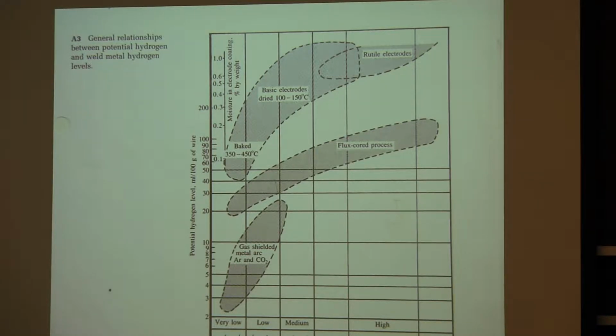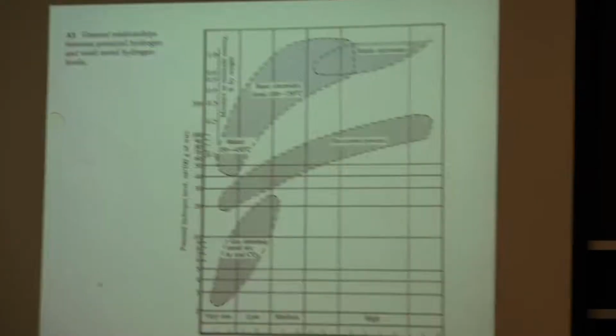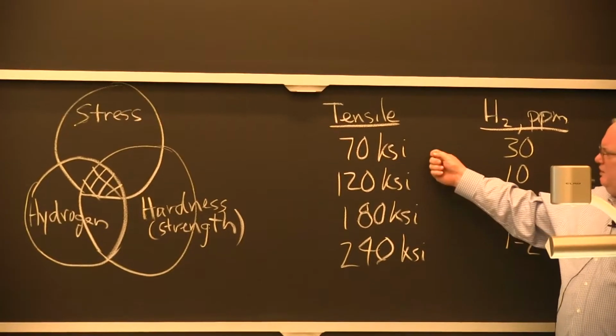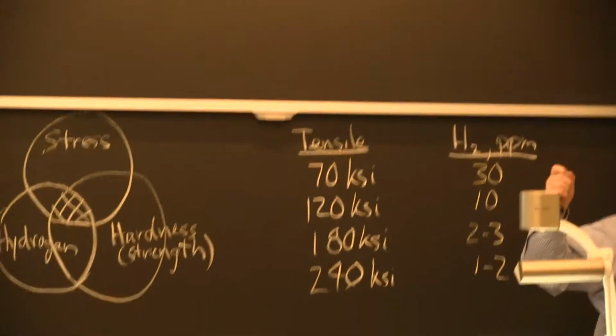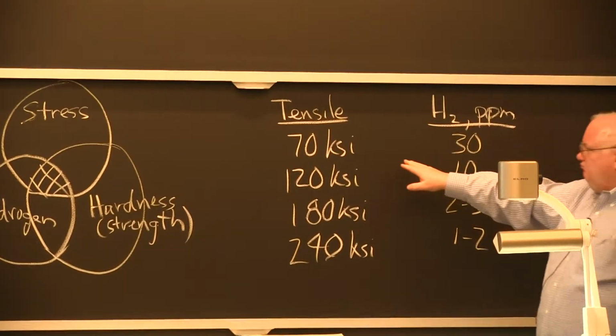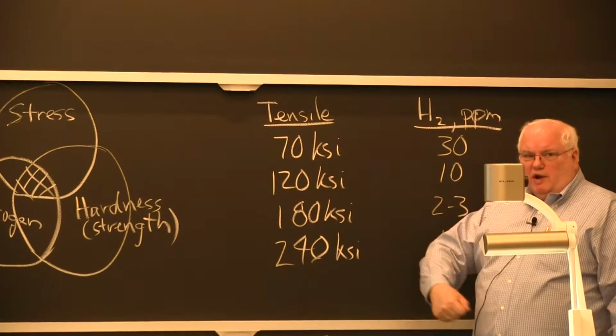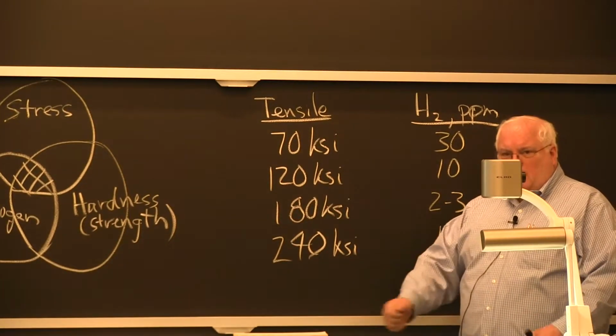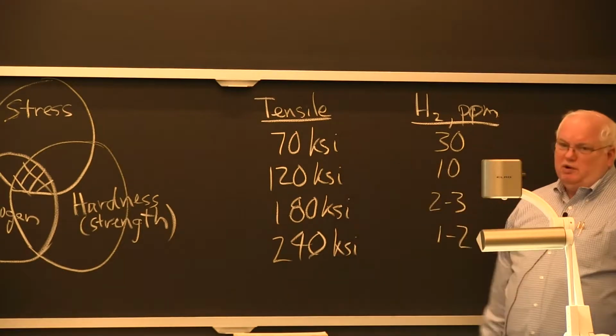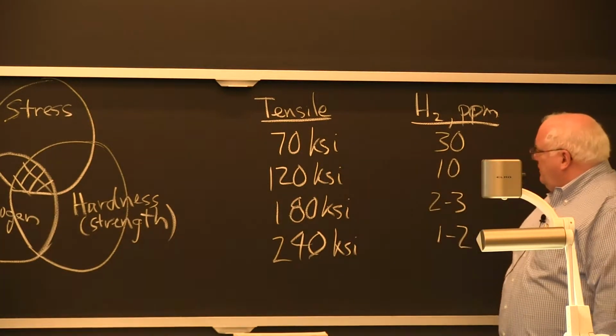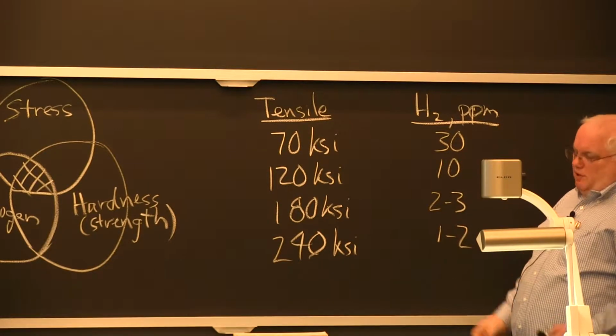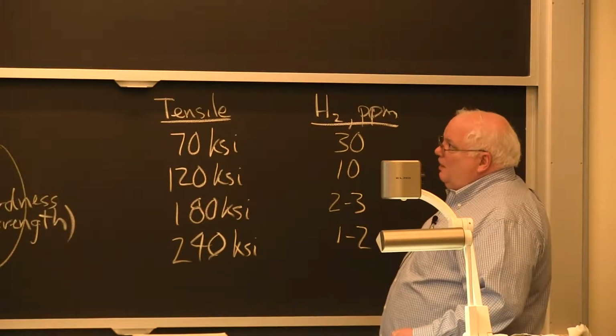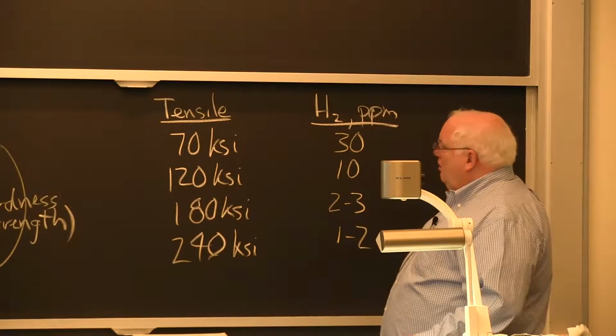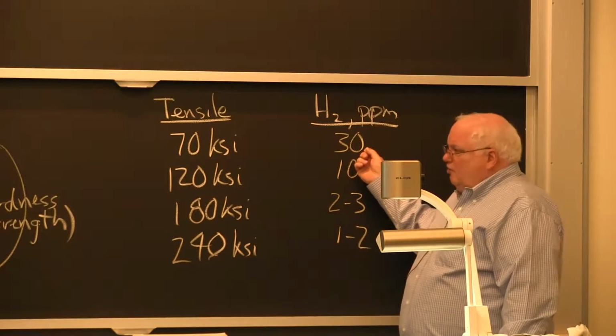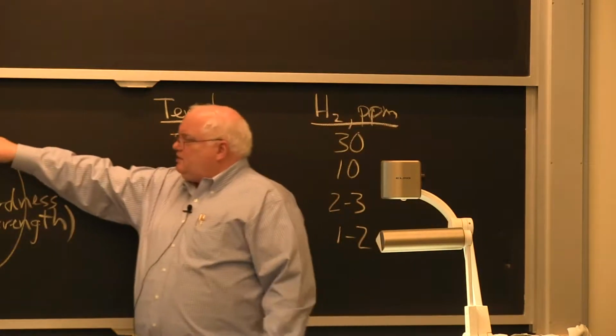And what I've done here is, if you actually deconvolute a lot of the data in the literature, you can come up with something like this. If I have a steel of 70 KSI tensile strength, and that's mild steel, that's what your little red radio flyer wagon that you pulled around as a child, or your typical cheap bicycle, is made out of, 70 KSI steel. You can tolerate 30 ppm, and you have to really use no hydrogen control at all to get enough hydrogen in there to crack it. And you have to have a high enough stress.